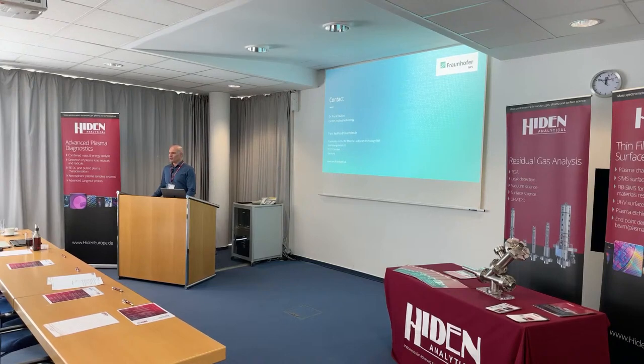No, we do it by some adhesive tape, only cleaning up afterwards. This is working fine. We are using a mechanical shutter system, it's just a shutter of metal sheet, and then we can just turn it into the plasma plume to cover. So when we know we would like to make some initial evaporation process when we start, then it's not necessary to make a tuning process or something like that. So we use the shutter, and then after several minutes, let's say 30 minutes, we open the shutter back. And so we prevent the process from getting covered by the DLC coating. Thank you.